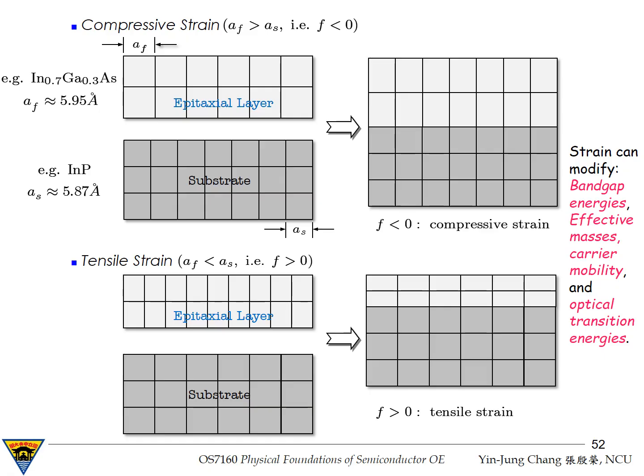Okay, so as we already mentioned earlier, coherent strain can only be maintained up to a certain thickness, which is termed critical thickness. Once the film becomes too thick, the accumulated strain energy becomes large enough that the crystal relaxes by forming the so-called misfit dislocations at the interface. So in the next part of our discussion, we will briefly examine how and why misfit dislocations form and how they help relieve lattice mismatch strain.